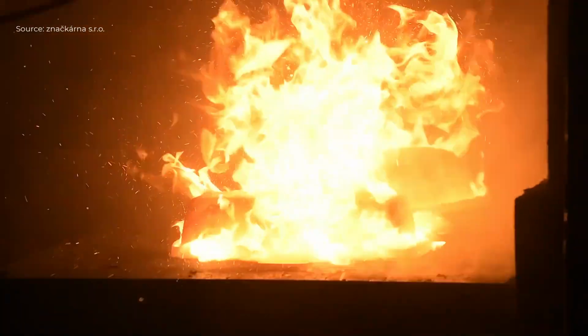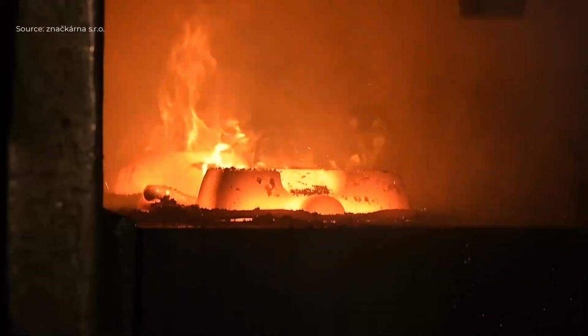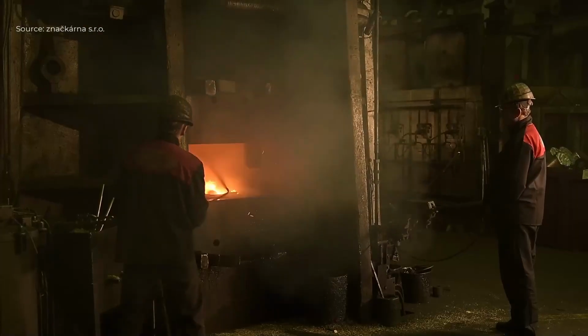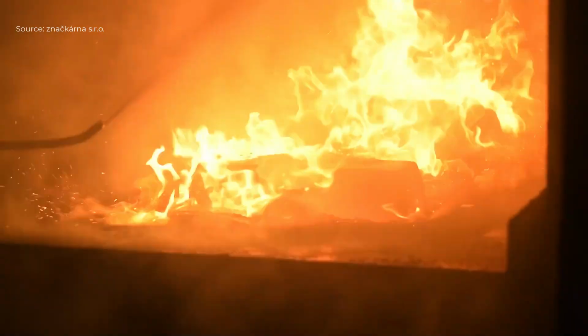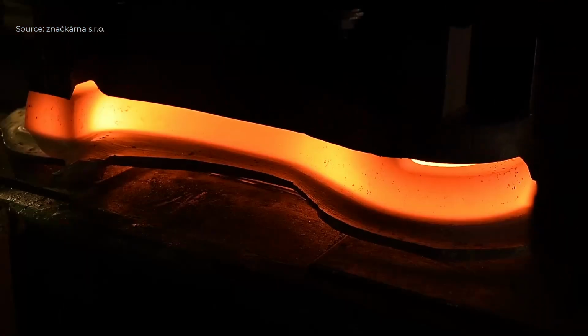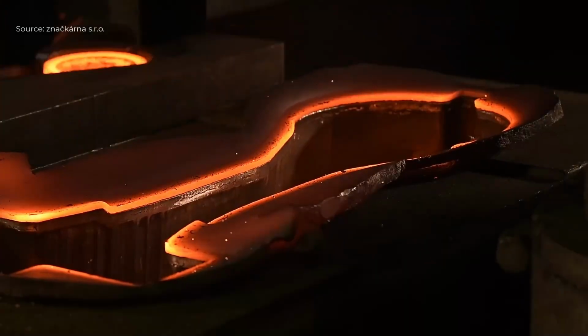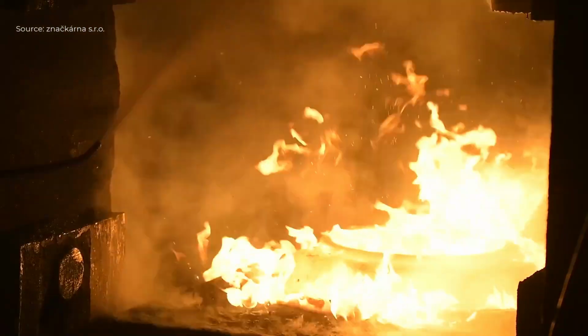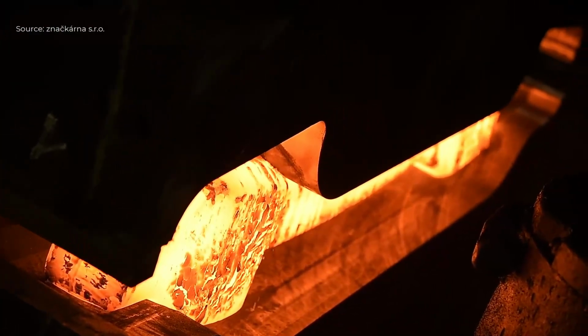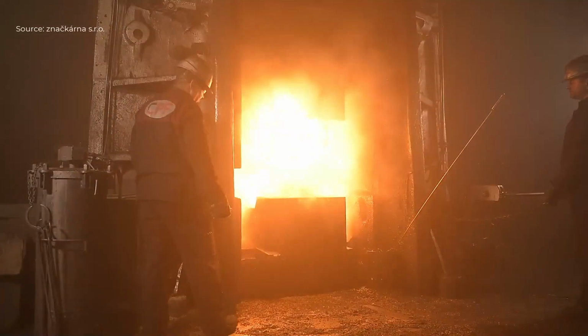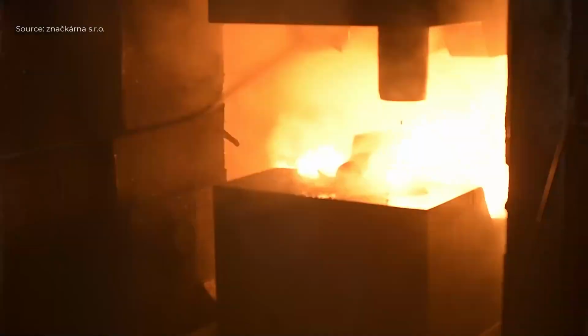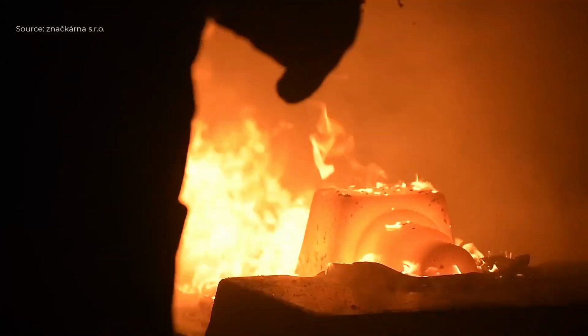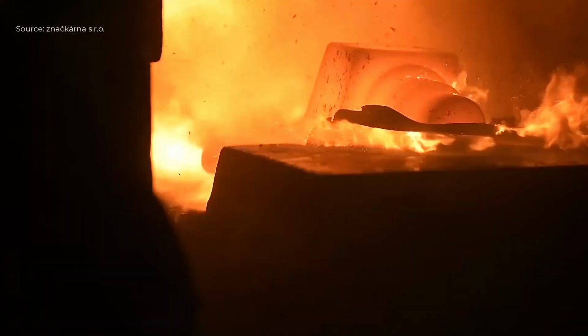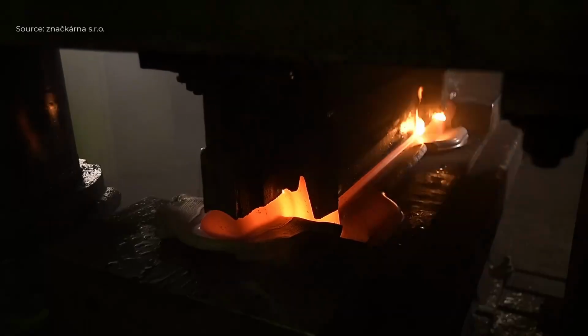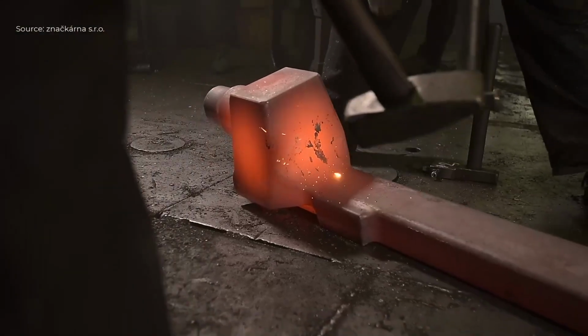This is followed by heat treatment to enhance the mechanical properties of the forged blank, such as hardness, toughness, and fatigue strength. Processes such as quenching, tempering, and normalizing are carried out in specialized furnaces. For quenching, forgings are reheated to the austenitizing temperature, typically 850 to 900 degrees Celsius for alloy steels, and rapidly cooled in oil, water, or a polymer quench to form a martensitic microstructure. Automatic quenching baths are equipped with agitators to ensure a uniform cooling rate, typically 50 to 100 degrees Celsius per second, to minimize residual stresses.